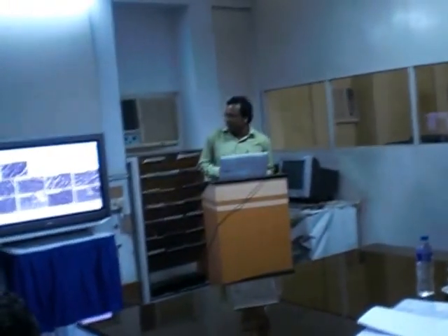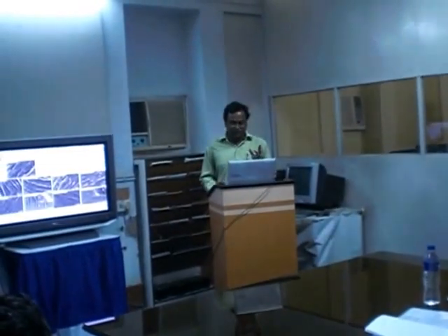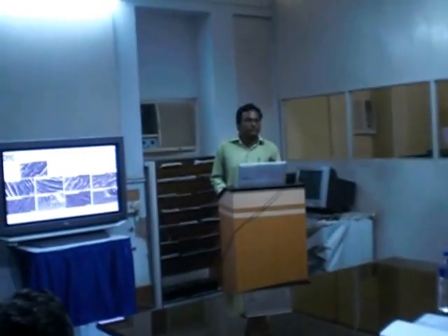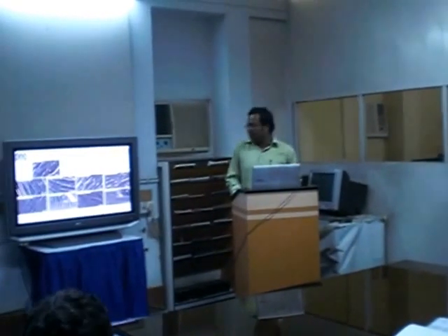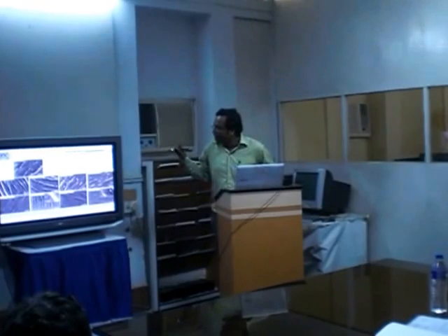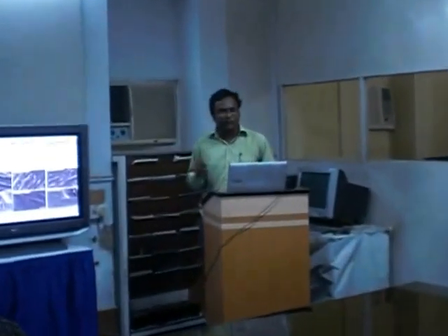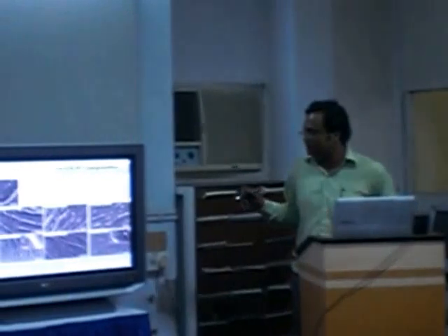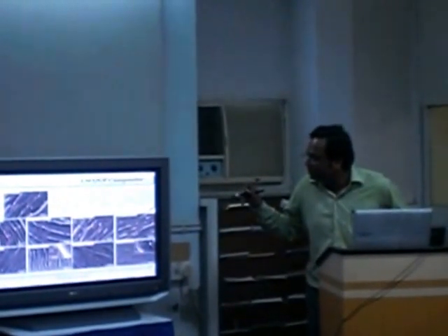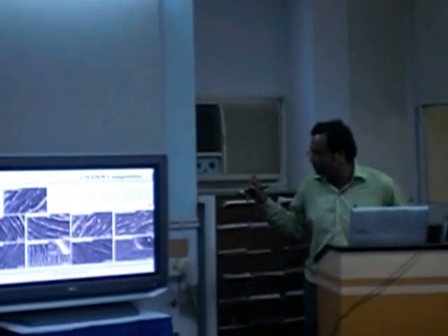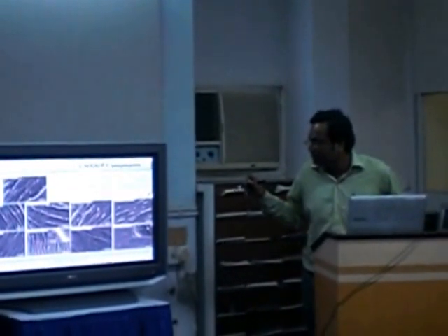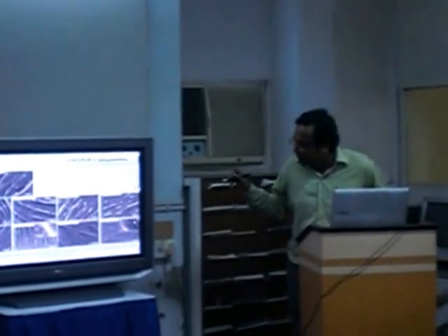And what we have done here, we have cross-checked the fracture surface of the polymer matrix. Actually, the possible agglomeration of the carbon nanotube creates stress concentration points within the matrix. And during the failure mechanism, the failure characteristics of the composite sometimes alter. With better dispersion and better mechanical property, we see a very branching, very thin, river-like pattern.